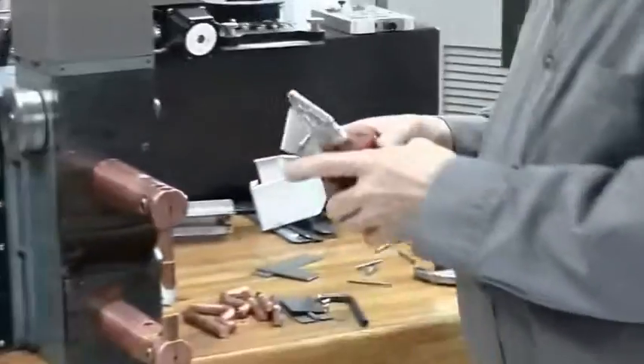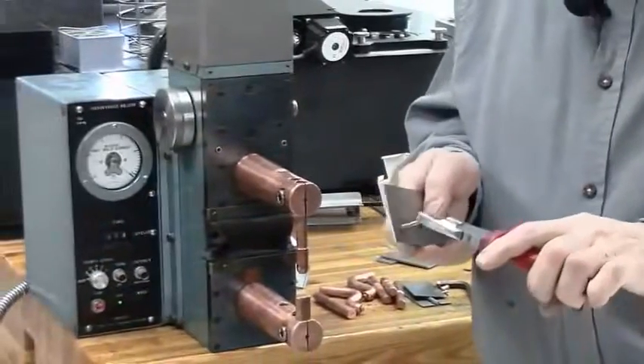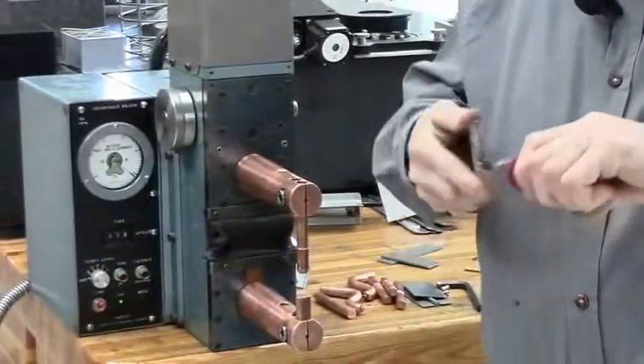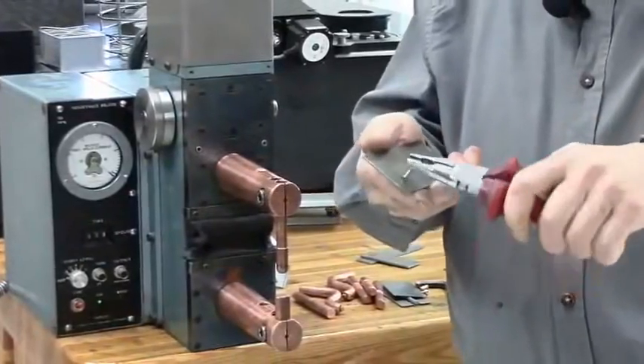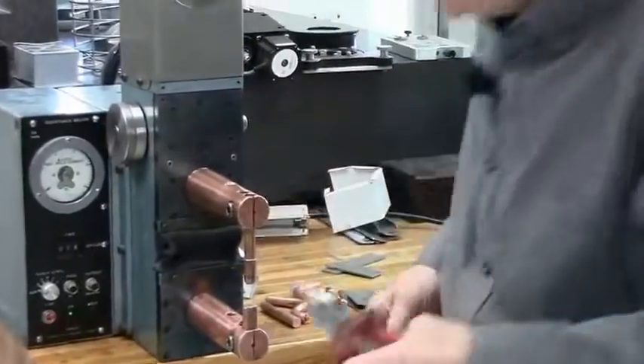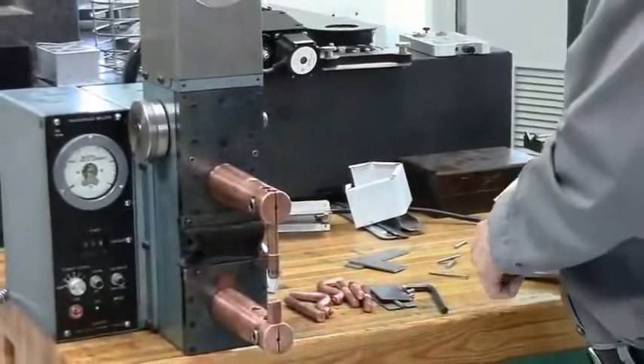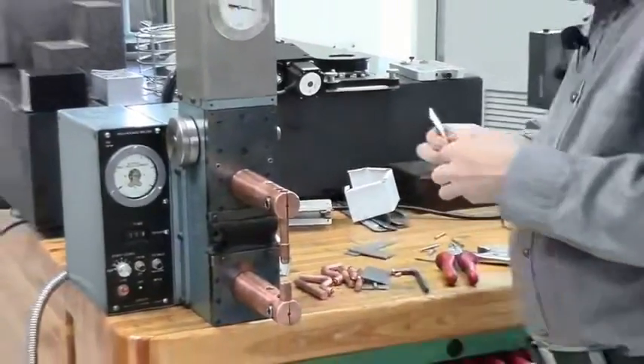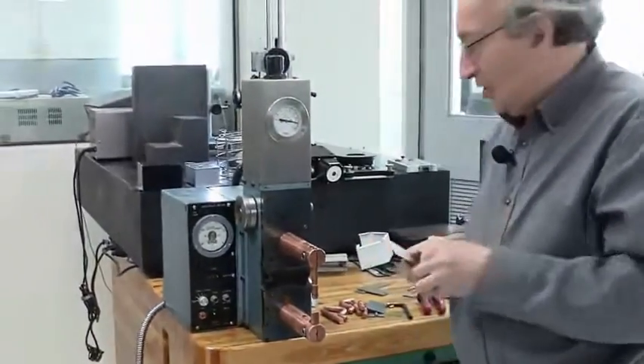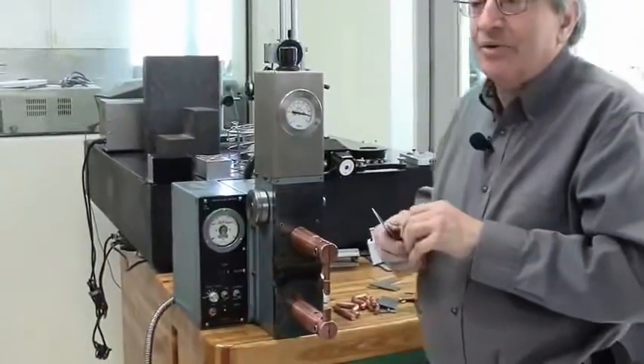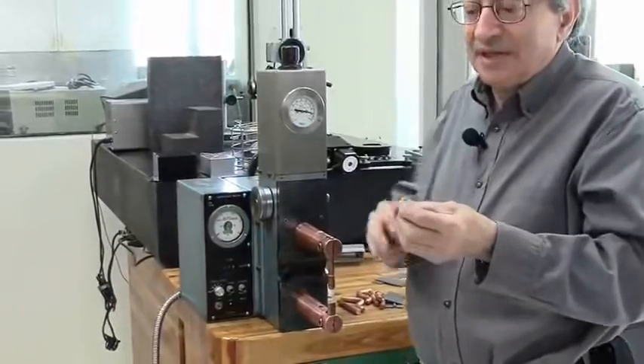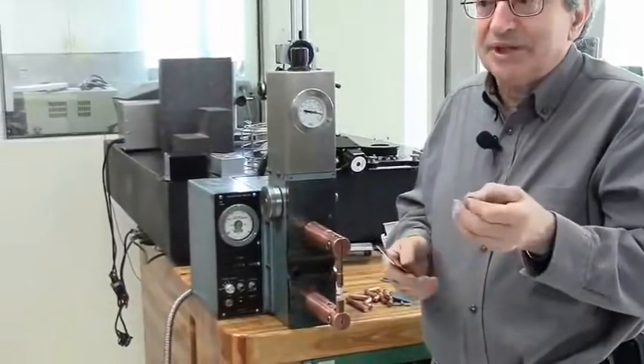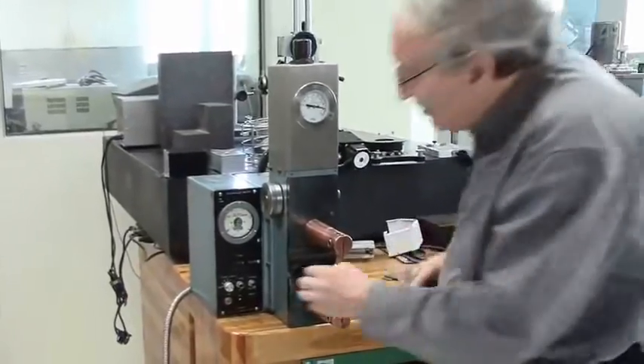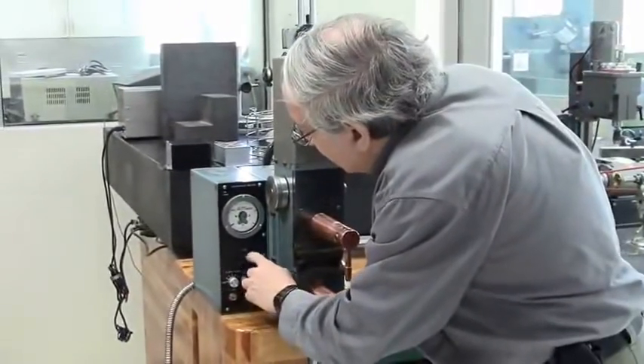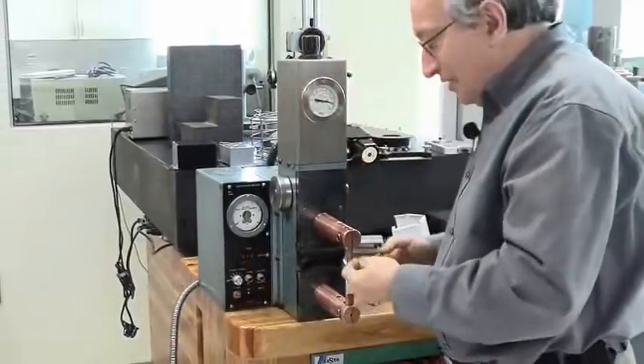Okay, so now you have a stud, and again, if you are not sure about the setting, you do the standard test. It has to break the studs without opening the weld. This one didn't. It opened the weld, so it had to go to a higher setting, maybe a 10. Okay, so if you don't have the special weld studs, you can use a standard round head screw. Either Allen or Slot or Phillips, any screw with a round head works almost as well as a stud, except now we know we need a bit more current. So give it 12.